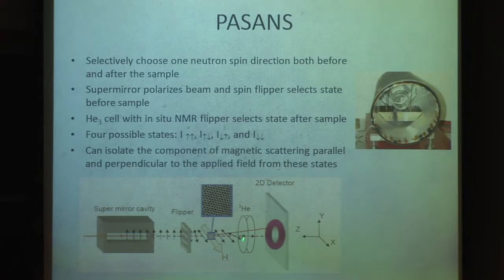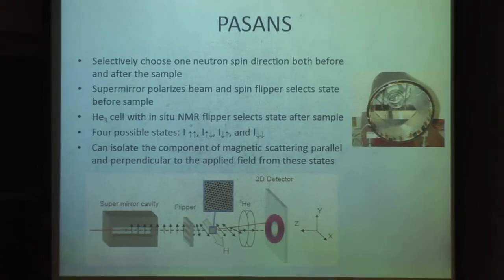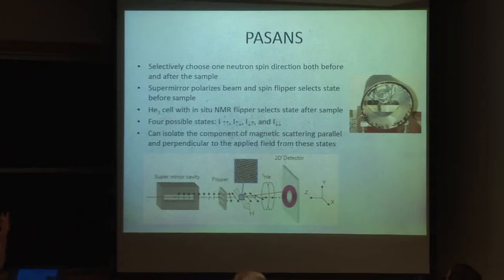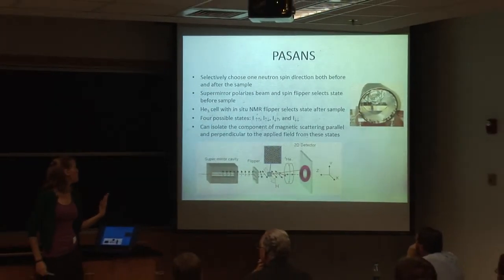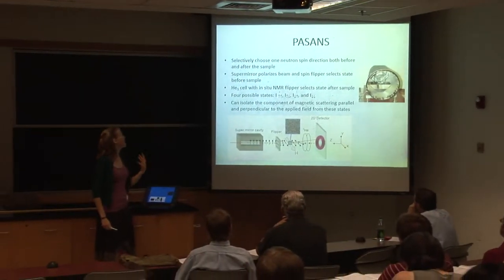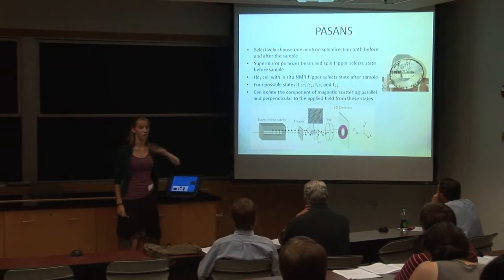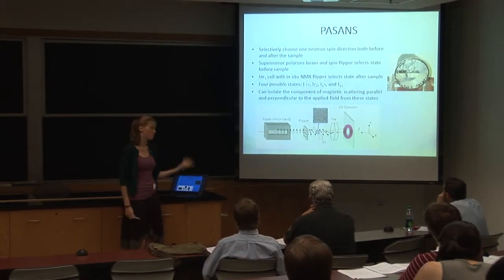Then we had a helium-3 cell, which is shown here, and an NMR in situ flipper after our sample to select, again, up or down. So using that, we got 4 possible states: up-up, up-down, down-up, or down-down. By combining these 4 possible states, we were able to isolate components of magnetic scattering, both parallel and perpendicular to our applied magnetic field.